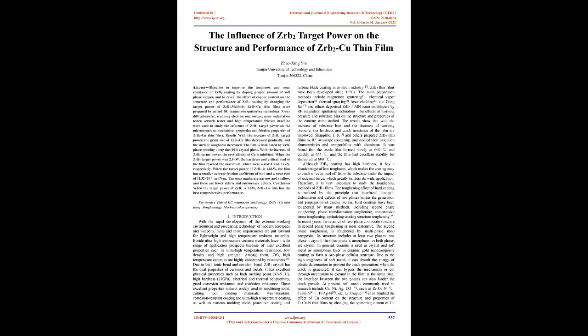ZrB2 thin films have been developed since the 1970s. The main preparation methods include magnetron sputtering, chemical vapor deposition, thermal spraying, laser cladding, etc. Gong and others deposited ZrB2/AlN nano multi-layers by RF magnetron sputtering technology. The effects of working pressure and substrate bias on the structure and properties of the coating were studied. The results show that with the increase of substrate bias and the decrease of working pressure, the hardness and crack resistance of the film are improved.